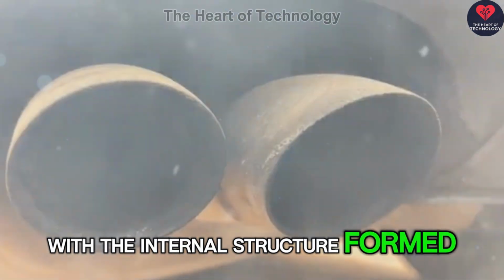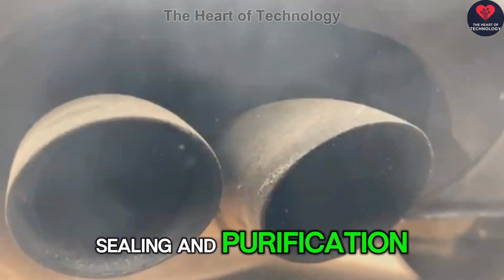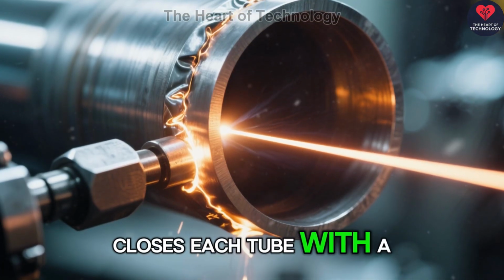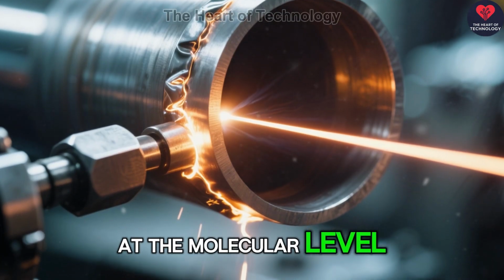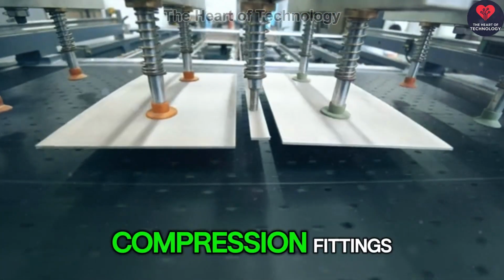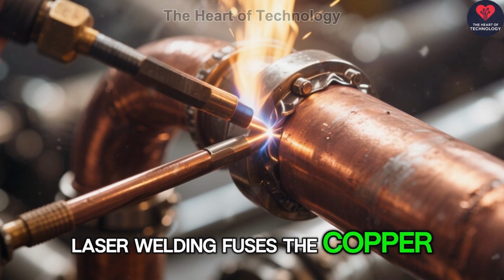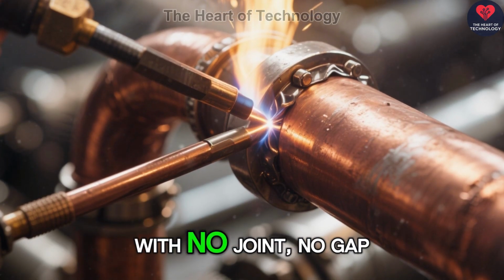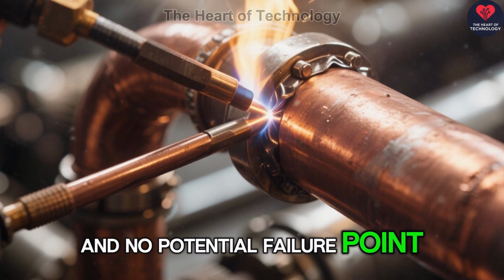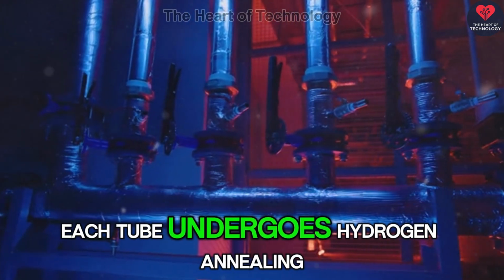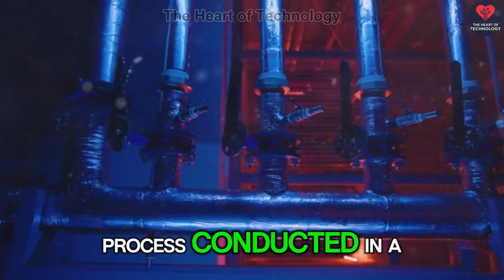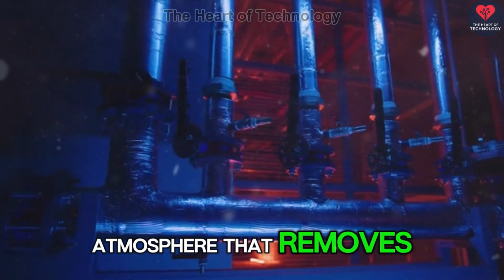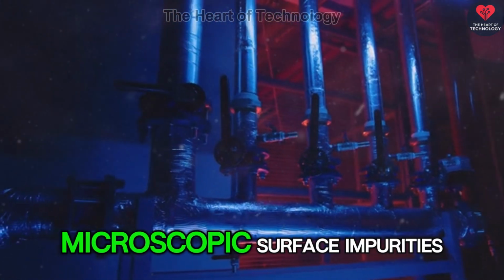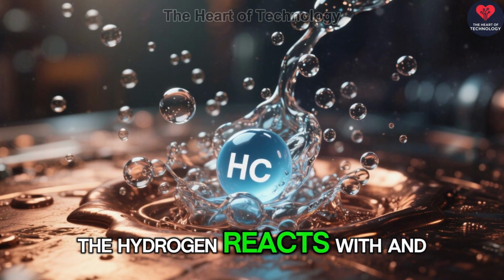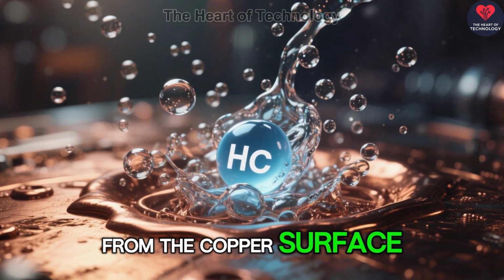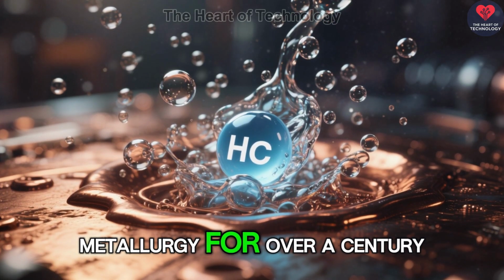With the internal structure formed, the heat pipes move to sealing and purification. Laser sealing closes each tube with a bond that is airtight at the molecular level. This is not the kind of sealing you do with adhesive or compression fittings. Laser welding fuses the copper itself, creating a continuous metal surface with no joint, no gap, and no potential failure point. Following the seal, each tube undergoes hydrogen annealing, a heat treatment process conducted in a hydrogen-rich atmosphere that removes residual stress from the copper and eliminates microscopic surface impurities. The hydrogen reacts with and removes oxygen compounds from the copper surface, a process that has been used in precision metallurgy for over a century.